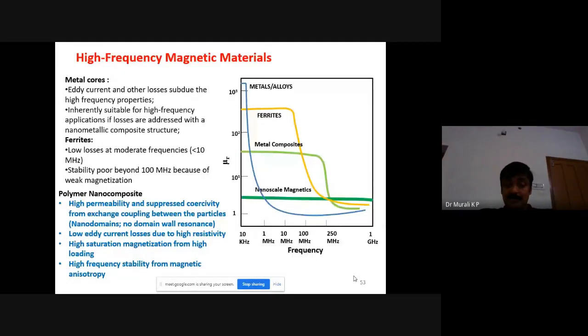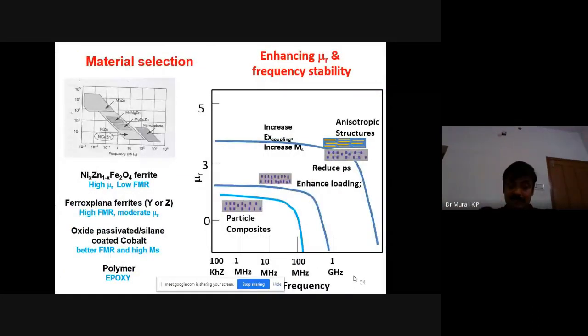So how is it possible? These are the materials which can be taken for these applications at different frequencies. How to enhance the frequency stability and reduce the loss? These are the strategies we can take. First, reduce the particle size to below the single domain size, because once you reduce the particle size below the single domain size, there won't be any domain resonance. And reduce the particle size to a level so that exchange coupling will increase. So that can enhance the saturation magnetization, as well as the initial mu.